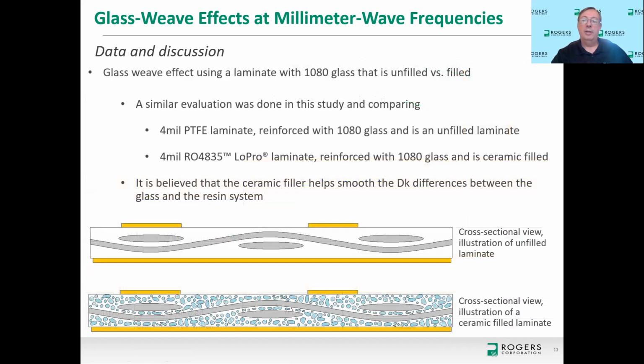Now moving on, looking at the 1080 glass in more detail, and now looking at 1080 glass of an unfilled laminate compared to filled laminate, that's a little bit more interesting. So far, the data I've shown you on the 1080 glass was actually an unfilled laminate. It was PTFE and glass only. However, the other laminate that I want to compare it to is the RO4835 LoPro laminate, and that is also using 1080 glass, but it is a highly ceramic filled laminate. So there's a lot of ceramic particles in this laminate.